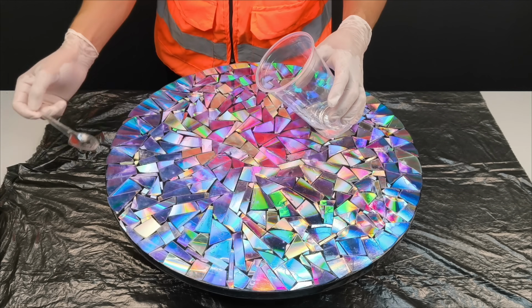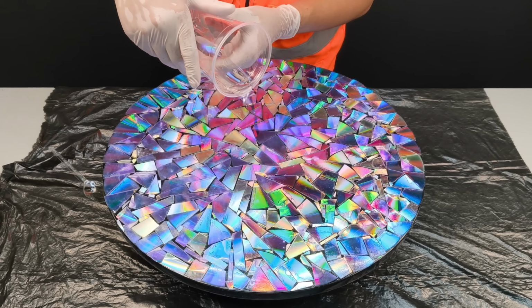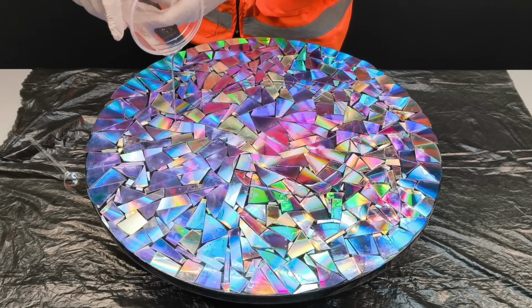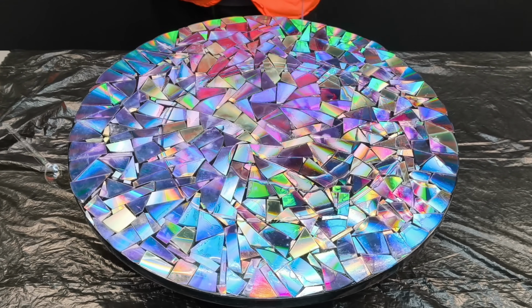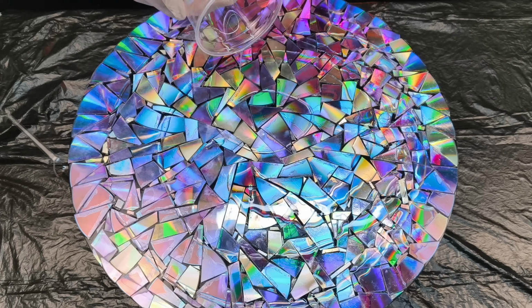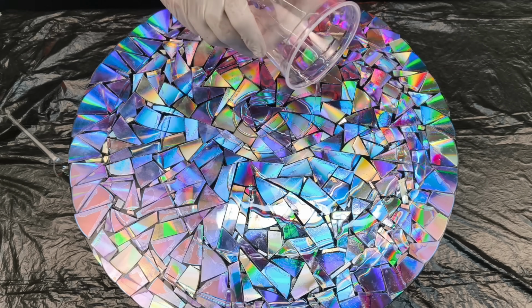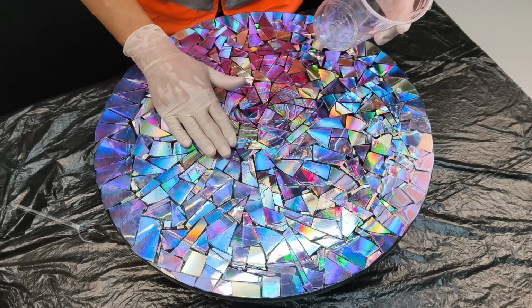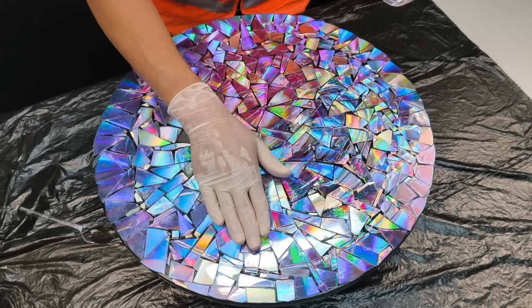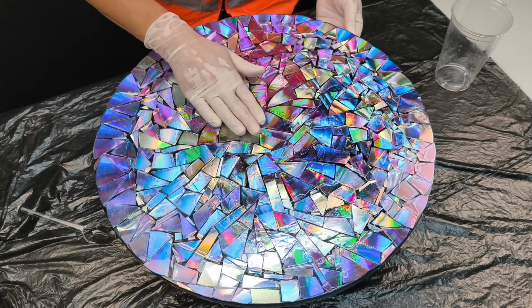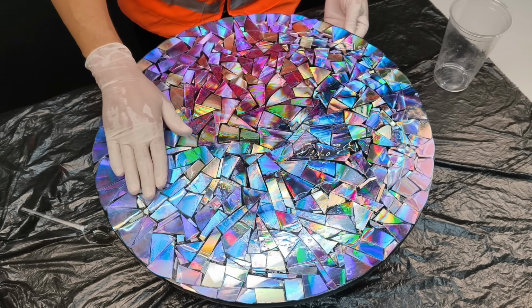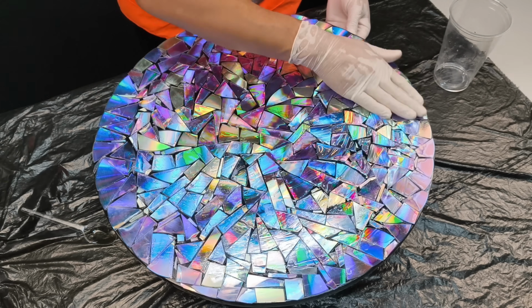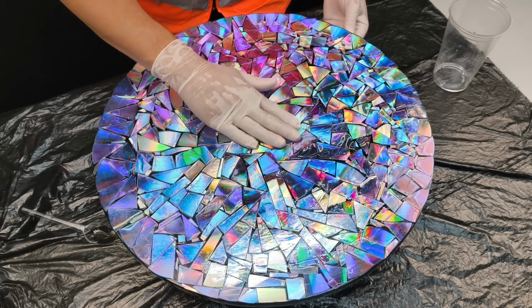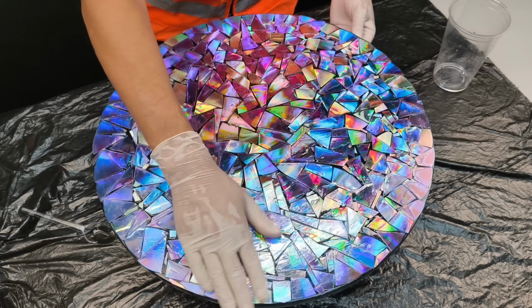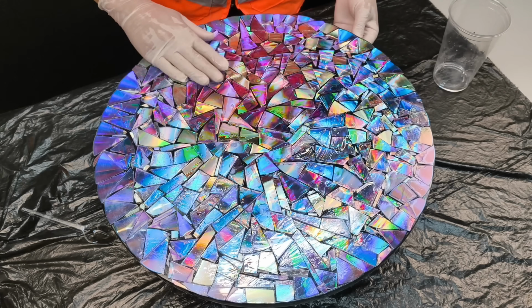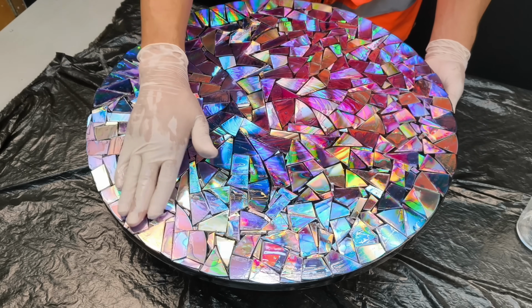As mentioned earlier, this first resin application is solely for sealing. The ideal interval for the second coat is about 3 hours, when the surface is still tacky and not fully cured. At this stage, use latex gloves for safe handling and better control. Apply with smooth, controlled motions, gently working the resin across the entire surface to ensure it penetrates between the CD fragments. Work piece by piece, ensuring even coverage and eliminating gaps. This step is essential to consolidate the base, improve adhesion, and properly prepare the surface for the final finish.